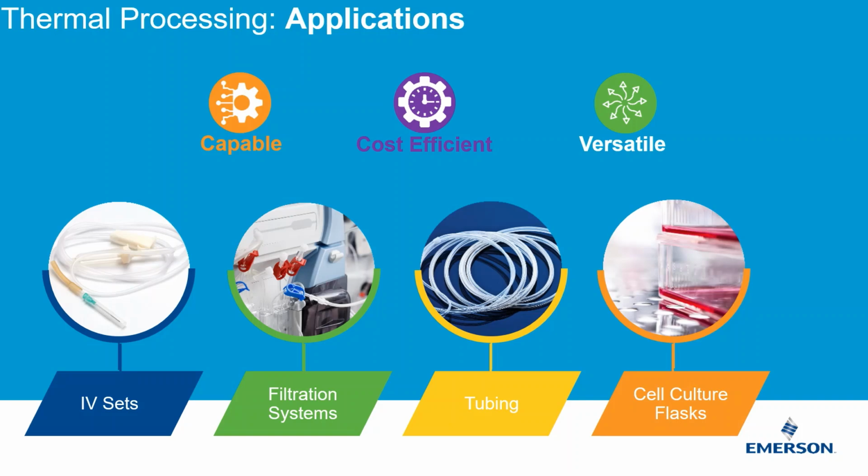One of the latest innovative technologies from Emerson is pulse staking. This process opens up new application possibilities because of the innovative design of the tips that can provide localized, changeable temperatures during the plastic forming process. Each tip combines an electrical heating element with a compressed air cooling system. The design instantaneously heats or cools the tip by applying pulses of heating or cooling that precisely manage the temperature of the plastic.